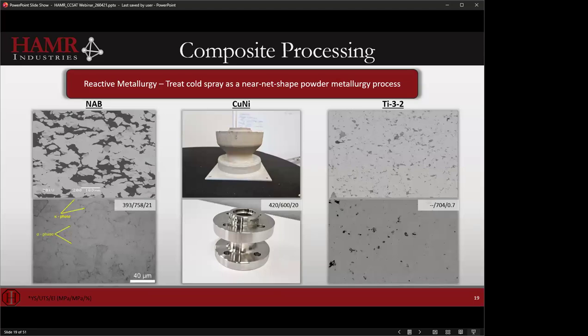Continuing on process, composite processing, reactive metallurgy is a very unique place that cold spray sits and that cold spray can leverage. So if we treat cold spray as a near net shape powder metallurgy process and look at it less through the additive lens and more through the powder metallurgy lens, then you can really do some cool things. I have three examples here of different materials that have been processed where a constituent blend, whether this be master alloy or CP elements or somewhere in between, is sprayed and then is reacted into the final alloy. You see an example of NAB, copper nickel, and grade 9 titanium or Ti-3Al-2.5V.